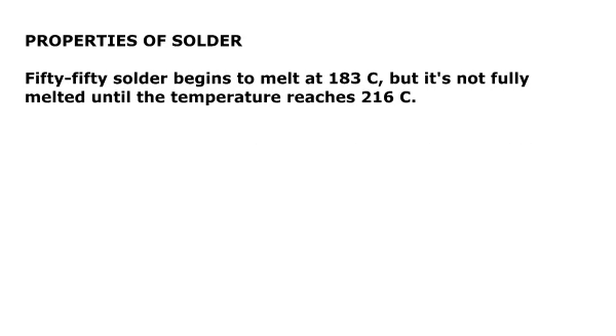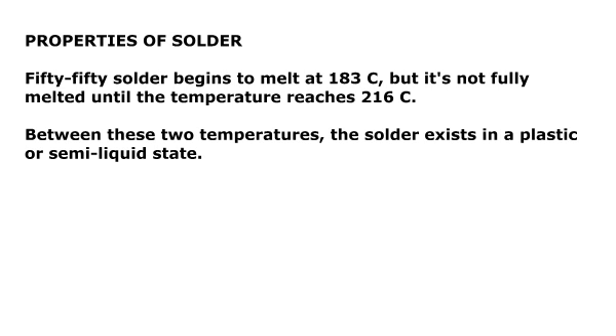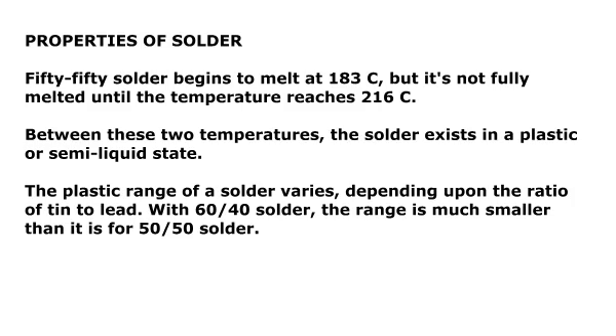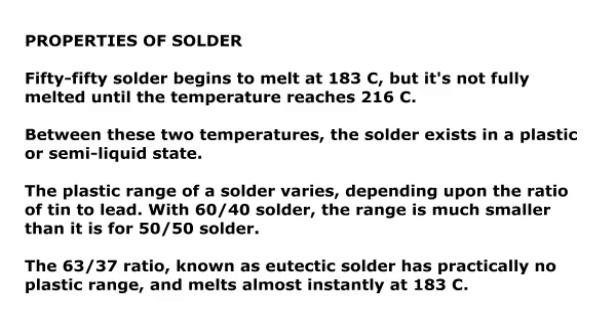50-50 solder begins to melt at 183 degrees centigrade, but it's not fully melted until the temperature reaches 216 degrees centigrade. Between these two temperatures, the solder exists in a plastic or semi-liquid state. The plastic range of a solder varies depending upon the ratio of tin to lead. With 60-40 solder, the range is much smaller than it is for 50-50 solder. The 63-37 ratio, known as eutectic solder, has practically no plastic range and melts almost instantly at 183 degrees centigrade.